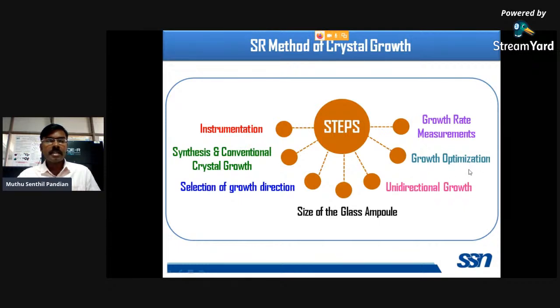We have to select two temperatures, one at the top portion and another at the bottom portion. The only thing is we have to maintain a uniform temperature near the seed crystal interface, and finally growth rate measurement. So we have to check the growth rate by applying different temperatures at the top and bottom portion. At the top portion, you maintain 35 degrees Celsius, what is the growth rate? 36, what is the growth rate? 37, 38, 39. Up to spurious nucleation formation, we have to check the growth rate along different directions, different orientations and with different temperatures.